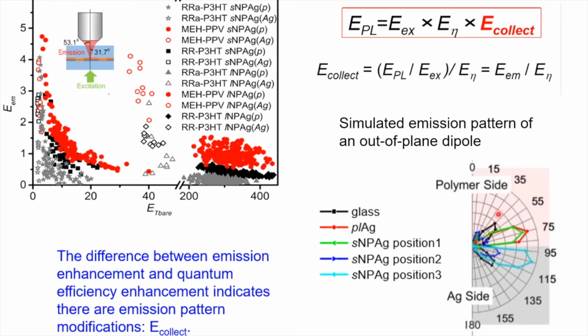And we carried out some electromagnetic simulations to dig into this aspect further. We found, for the most part, that the planar silver would direct the emission all to one side, to the polymer side. For the glass, it would leak both into the polymer and into the glass substrate. And for the porous metasurfaces, the emission would be very unpredictable depending on pore size and would often leak preferentially into the polymer more than into the glass, except for certain positions of the dipole if you put them very close to the glass in the center of the pore.